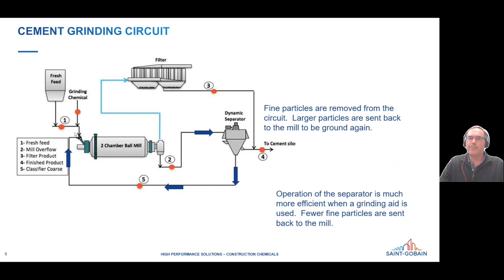And so what the grinding aid does is it makes the separator act more efficiently. So normally, if you don't have a grinding aid, particularly, a lot of fine particles that should be taken away into the cement actually end up going through and getting ground again unnecessarily. So this could happen because they're agglomerated into larger particles, or they may be stuck to a larger particle. So in any case, a lot of them get carried back.